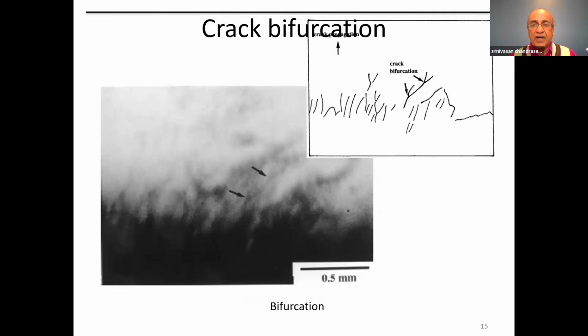These finger-like features are very characteristic of bifurcation of a crack. Whenever a crack travels, it's like a fork in the road. If it decides to go in 2 or 3 different ways, that's called bifurcation. That bifurcation is always characterized by finger-like features. So when you see finger-like features ahead of a crack front, it always means that the crack is bifurcating.